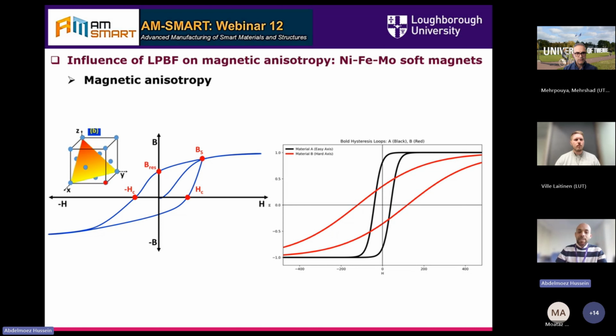So let's summarize this as a different response of the internal magnetic properties of the material according to the applied magnetic field direction. And this is like a hysteresis loop. This is what we need from soft magnets, for example, and it is a good example of magnetic anisotropy. So for the black one, the material starts to saturate when I apply a small magnetic field, probably at this point, 100, and the coercivity is low. So this is good for a soft magnet. However, for the same material, when we change the direction of the applied magnetic field, it's almost not saturated, and even the coercivity is a little bit high.